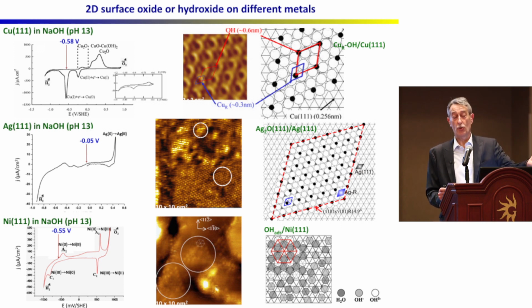So it's a precursor to the formation of the oxide, so that the oxide that is forming has the memory of this structure, which is formed at a potential below the formation of the oxide. And we looked at something similar on different metals.